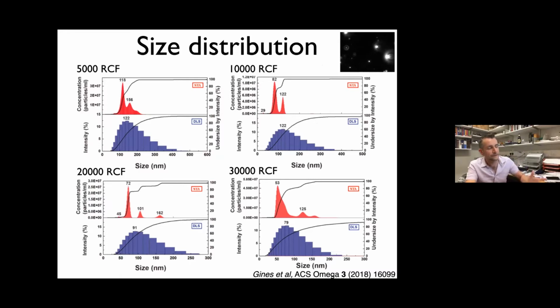So when you've milled your stuff, you centrifuge it, and then you look at what you've got. So the main technique people use to do this is dynamic light scattering, right? Which is pretty standard, and it's very, very good. It's very effective, but you've got to be very careful, because the problem with light scattering is that the intensity of scattered light is proportional to the size to the power of 6, right? So if something is 10 times bigger, it scatters 1,000,000 times more light. And so the upshot of that is that when you put a sample into your DLS, if there are a few big particles in that sample, it will totally swamp your spectrum. And that's kind of what you're seeing here.